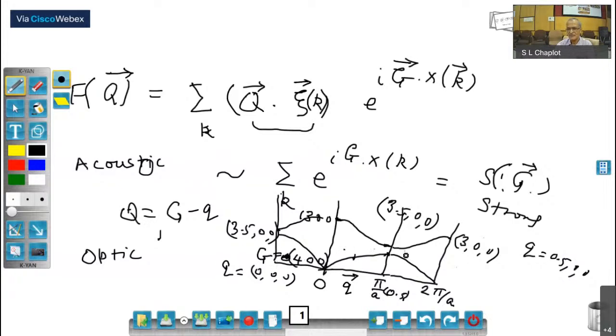It can be done on the basis of some simple arguments, and often one starts with values where the Bragg reflections are very strong, and then goes from a strong reflection to a weak reflection. The acoustic mode is measured around a strong Bragg reflection, and the optic mode may be measured around a weak Bragg reflection.